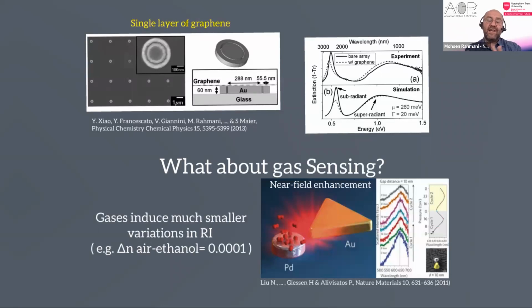But the issue is that when we go to gas sensing, the story is different, because these nanoparticles can detect solids or liquids, and they really work well. They change the refractive index around the nanostructures when solid or liquid materials are present. But when we are speaking about the existence of gas, the change they make in the refractive index is really, really low. For example, one example I have put here: the change in the refractive index between air and ethanol is 10 to the minus 4, which is really little, and it's hard to use metallic nanoparticles or plasmonics for gas sensing. Of course, some nice strategies have been proposed by the group of Harald Giessen many years ago.